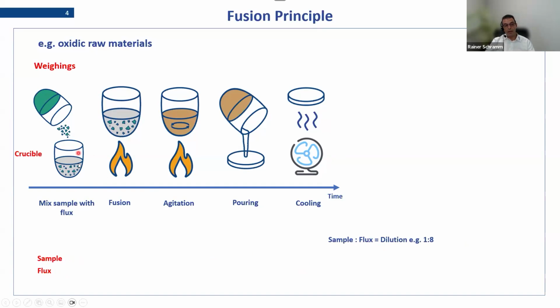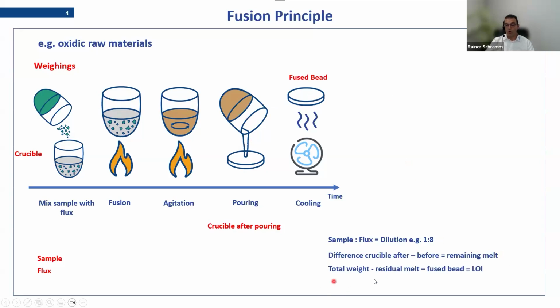Additionally, we could weigh the empty crucible, we could weigh the crucible after pouring, and this of course will tell us something about how much material was left in the crucible. And if we then also weigh the fused bead, then from all this information, we could also calculate a loss on ignition of the whole process. Some people are doing this. This is why I just wanted to mention it here.